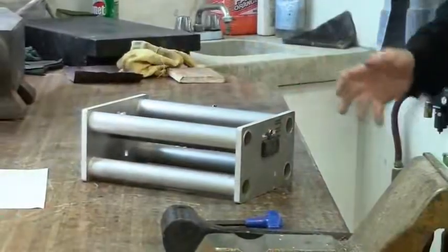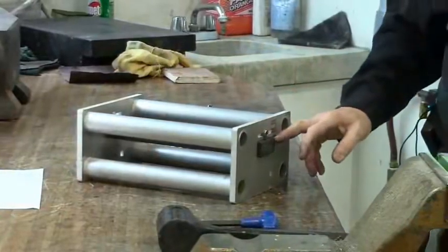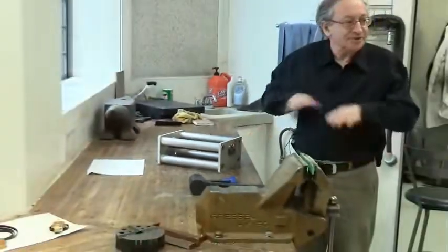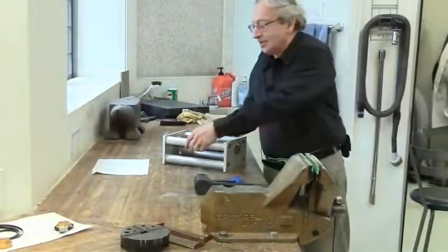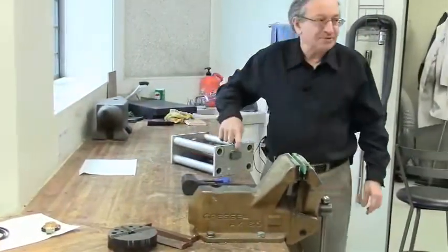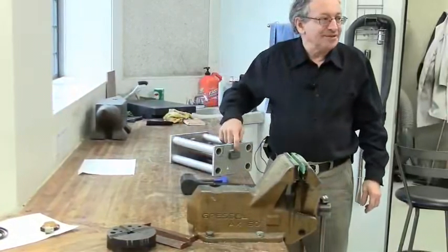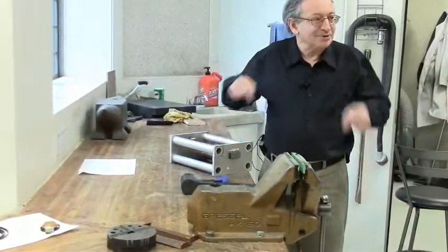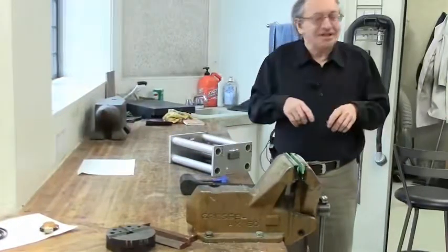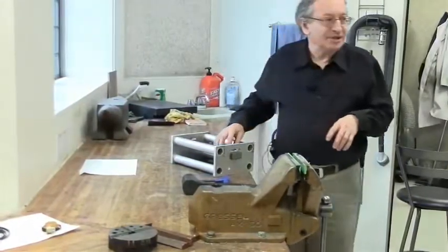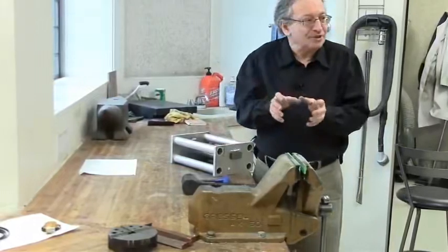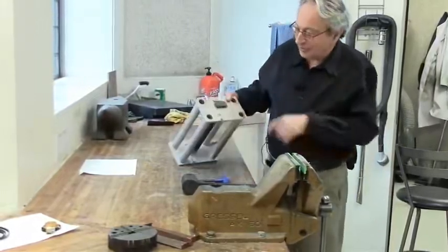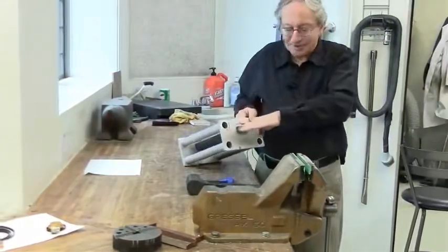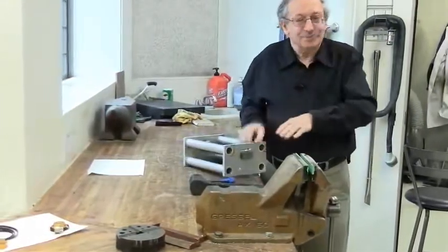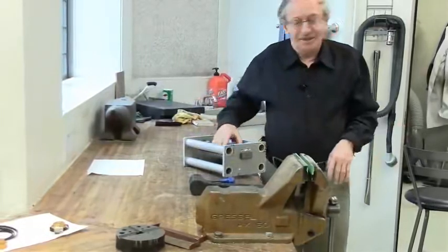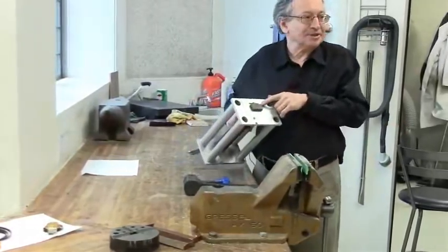And I can disassemble it, and it's a very, very good clamping system because it doesn't put local load, it spreads the load. Say the inexperienced person would put a set screw in, and that's a very bad idea because the set screw would crack the granite because it puts all the load at one point. And in any case it's not accurate, even if it wasn't brittle. It's not accurate because the set screw deforms it. It puts all the pressure on one point. While if you put this flexure clamp, it just expands in a gradual, very gentle arc and spreads the pressure on the whole granite. So any kind of flexure clamps are much, much superior to set screws.